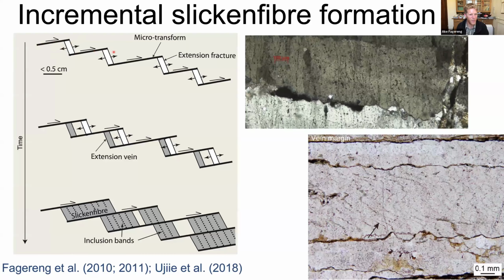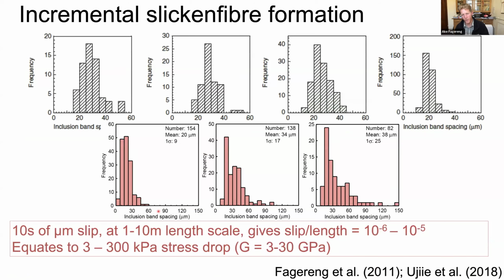Yes. Schematically, we have slip on multiple little surfaces. They are linked by dilatant fractures. Those have slip increments on the order of a few microns, tens of microns. So if we apply that and say, well, these slip surfaces have length scales of tens of meters max, they have slip of tens of microns. If we assume a shear modulus of a few tens of gigapascal, then that gives us a stress drop in the hundreds of kilopascal max. So very, very small stress drops,